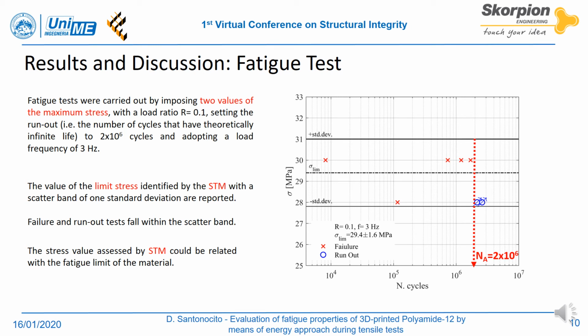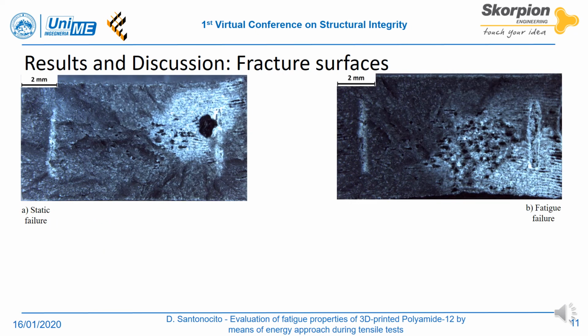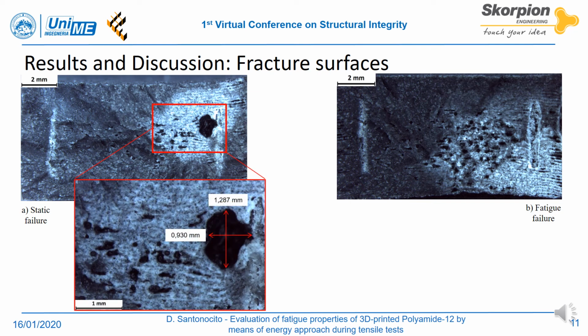However, several traditional fatigue tests have to be carried out to obtain the complete S-N curve and the fatigue limit of the material. After static and fatigue tests, the fracture surfaces have been evaluated through an optical microscope. As regards the static test, the fracture surface showed the classical aspect of a ductile failure with small plastic deformation. In all of the static fracture surfaces, a series of defects due to the lack of powder melting are clearly visible. In particular, a defect with a diameter of about 1 mm has been found surrounded by non-melted powder, where it is possible to distinguish the different layers.